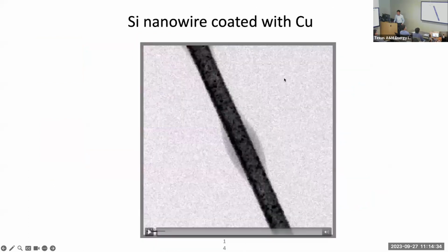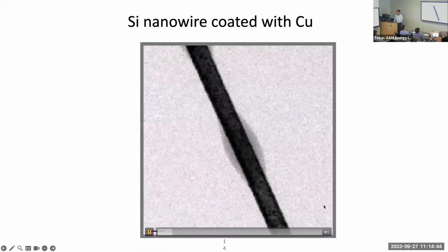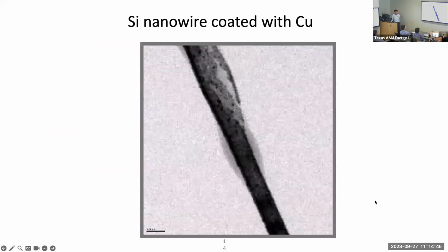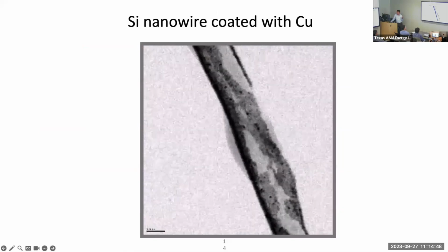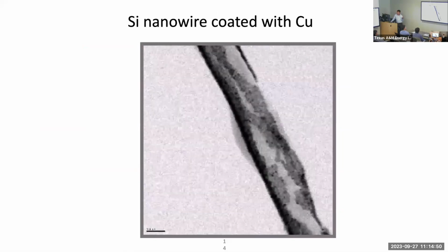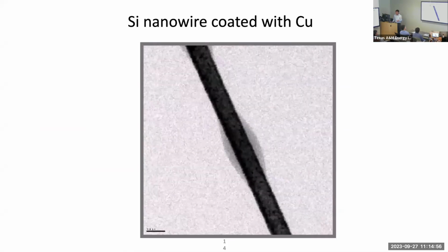Using this technique, we could really look at, when we charge, for example, this nanowire surface coated with copper, and you can see gigantic volume expansion taking place. The scale bar is 200 nanometers. The surface coating of copper is broken, but the nanowire survives without breaking.